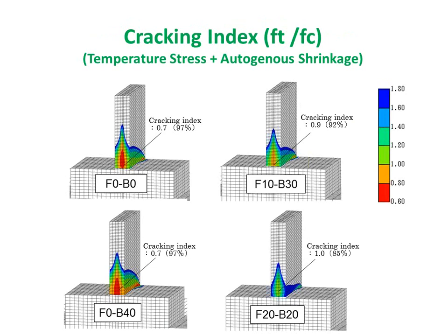And we calculate considering autogenous shrinkage. So the condition is more critical. If you look at F0-B0, 0.7. That's almost certain; we will have cracking in this case. And if you look at F20-B20, it's 1.0. Crack occurs or not occurs, that's a critical situation. So you can realize how the autogenous shrinkage affects the cracking performance of the